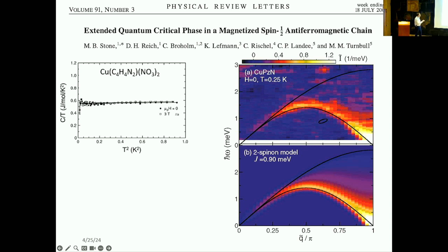It's a very subtle thing, but it has very specific consequences in neutron scattering, and those are shown here. So this is the wave vector and energy dependence of the scattering. It's quite an old measurement, actually, but what one finds is that for a given wave vector transfer, there's actually a range of different energies possible. So you have to know the resolution of the instrument. That is the resolution of the instrument. And then you'll notice that this is actually broader in energy than could be accounted for by a spin wave type excitation.